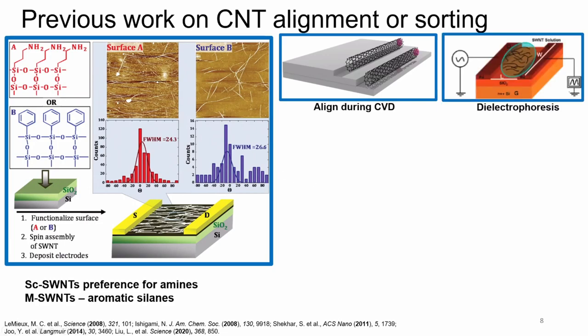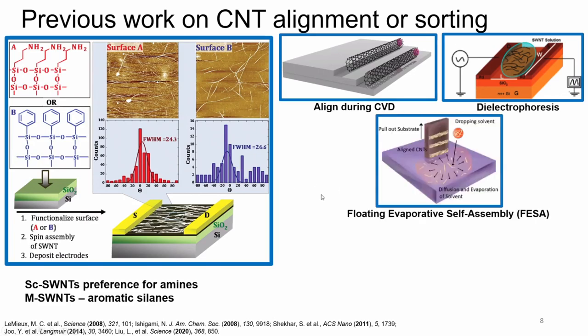There's also dielectrophoresis, and that presents an avenue for separation of the different metallicities. So you can separate the conducting and the semiconducting. You can also have patterning, but it's very difficult to scale in this method. There's also a technique called FESA, which is floating evaporative self-assembly, and that showcases semiconducting carbon nanotubes in an ink deposited on a water interface with vertical pulling. This results in bands of aligned semiconducting SWCNTs, but it's not all throughout the surface. It's in bands throughout the substrate.